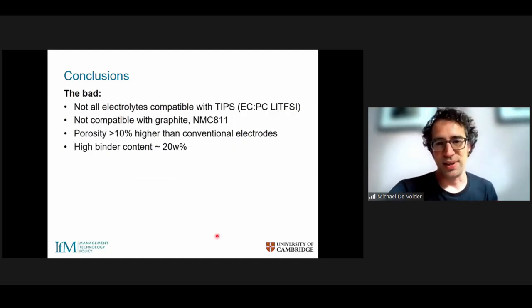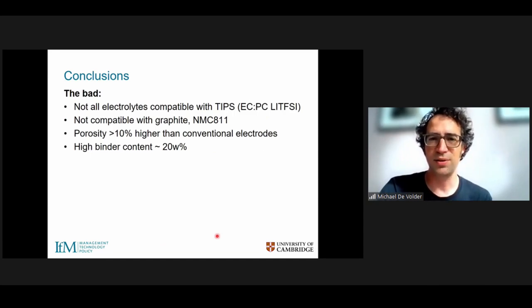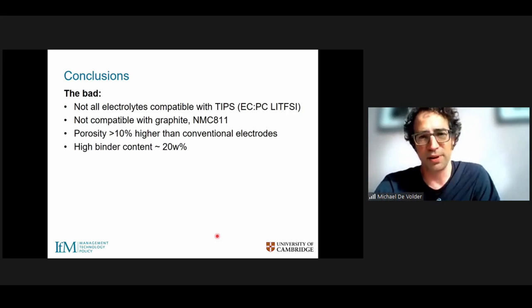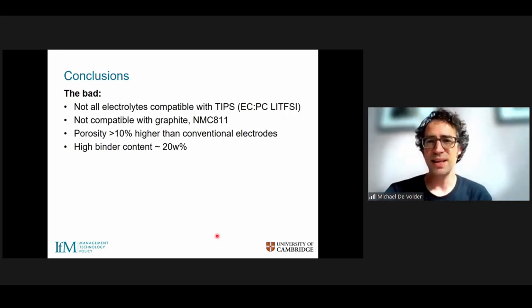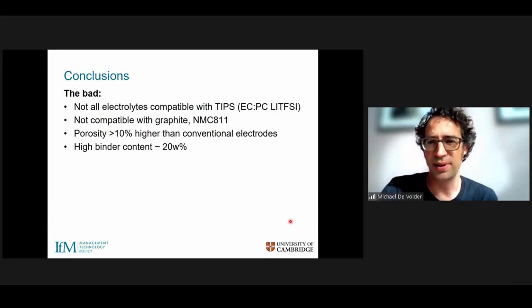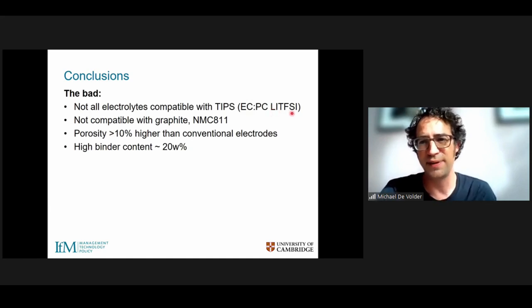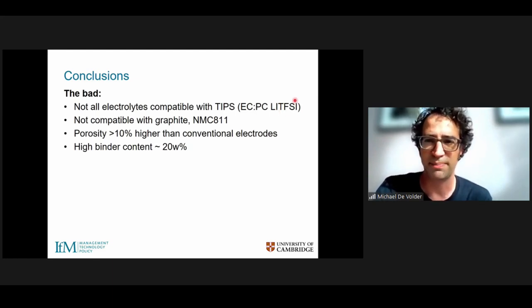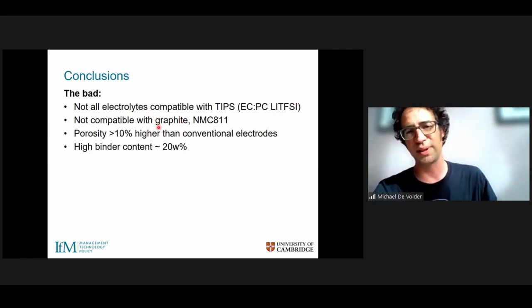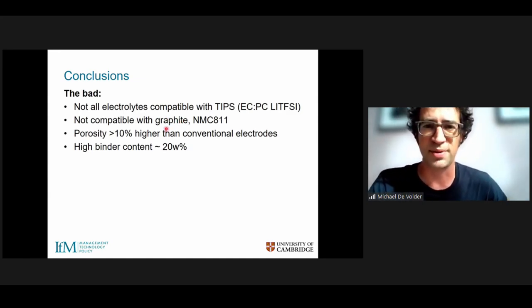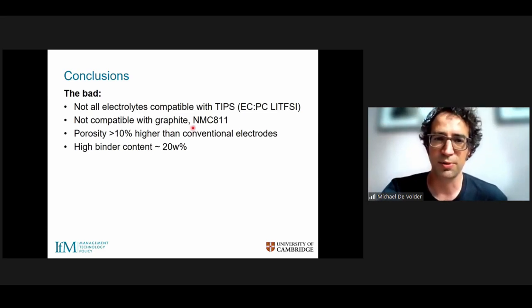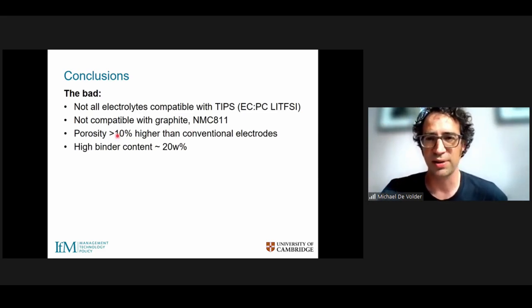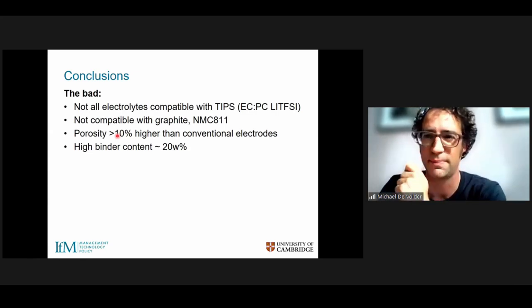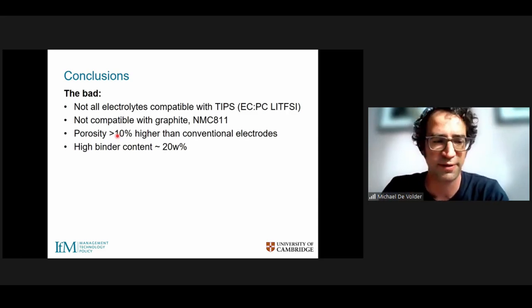There are some limitations to this process as well, which is that you can't use all electrolytes. They need to be compatible with the TIPS segregation process. And so in our case, we used an electrolyte called lithium TFSI. It's a salt we are using, which is a bit different from what most people use in batteries. I think it's slightly more expensive, so it's a small disadvantage. And the process we developed is also not compatible with certain materials like graphite, which is oftentimes used in batteries. And so that would require more work. Also, as I mentioned, working on the porosity and keeping the porosity as small as possible is important for the overall volumetric performance of our battery.